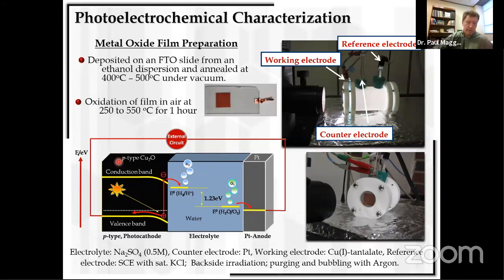And I've shown it by comparison to P-type copper oxide here, where copper is 1+ as well. In this case, the bands are bending down because it's a P-type semiconductor rather than N-type. And this is the same behavior we see for all of our copper 1+ semiconductors. Upon irradiation, the electron and holes are separated at the surface, driving proton reduction to molecular hydrogen, and then the opposite carrier makes its way to the counter electrode and drives water oxidation. This is the case for a P-type semiconductor.